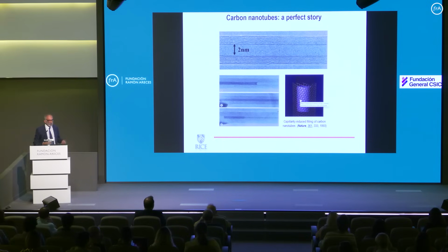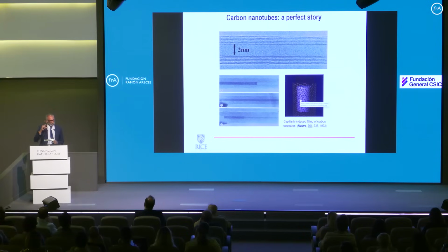But the point I was trying to make is that suddenly people figured out that you can have these amazing, perfectly crystalline tubes with a nanometer dimension that are made of pure carbon. And not only that, Iijima, who was looking at these structures, also realized that the lattice can be oriented differently with respect to the axis of the tube. So if you follow the hexagons around the tube, you can have different levels of chirality or orientation difference with respect to the axis. And some of the theoretical calculations done early on suggested that changing the chirality not only changes the structure, but also changes the electronic structure. So it was found for the first time that the same carbon tube with different lattice twists can exist as metallic tubes, semiconducting tubes, and so on and so forth.